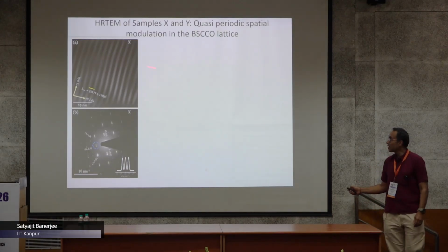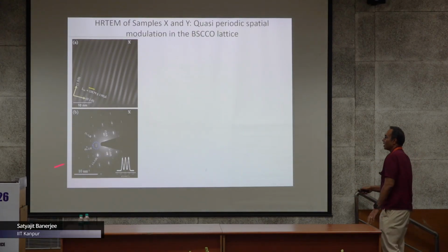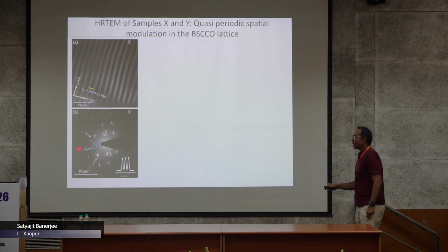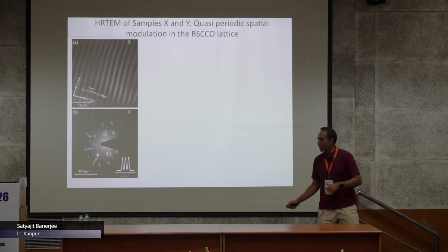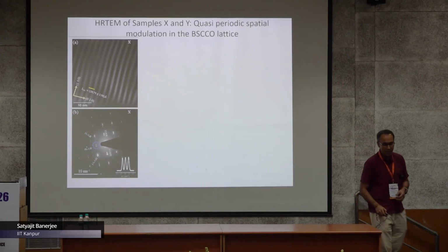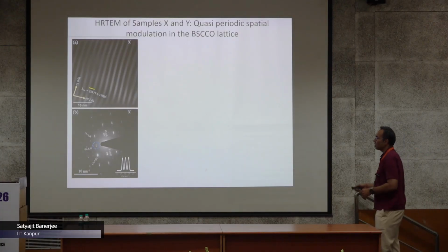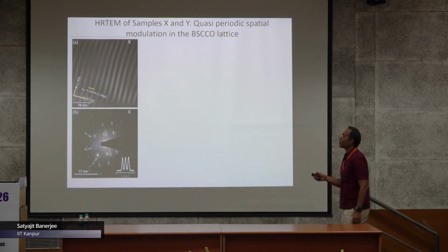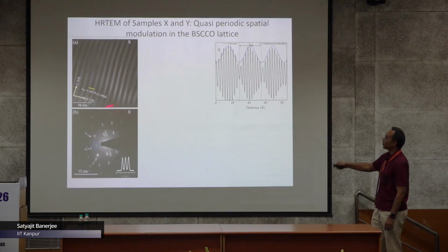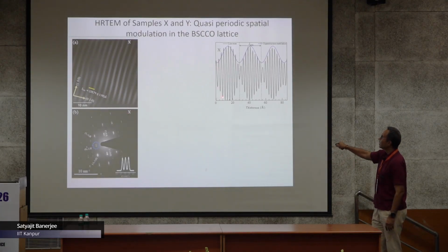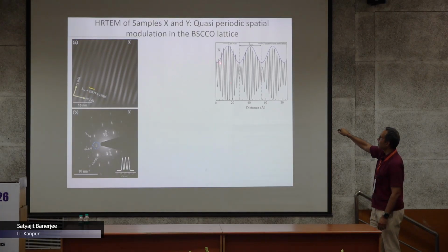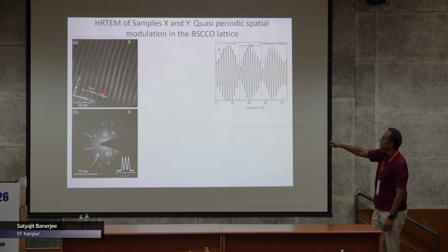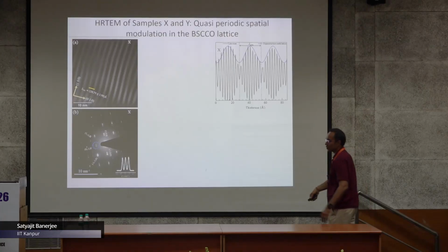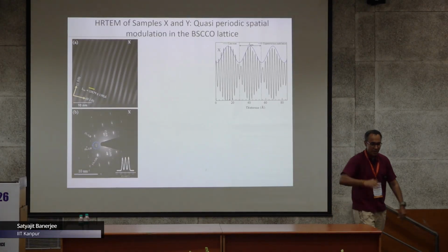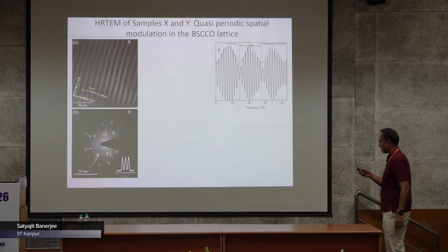These are in the sample we call X. If you look at the full width at half maxima of these satellite peaks, they are pretty sharp, and we see them all over the crystal over large distances. If you take a line cut, each of these modulations is picking up an atom in the system, and the overall modulation you see is this periodicity in the contrast. So there is an inherent 28 nanometer periodicity in the crystal.